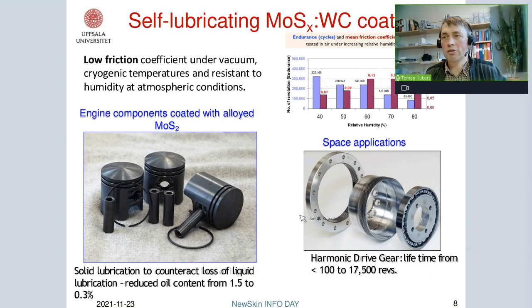Anyway, I start from an example of a coating developed by Tecnalia, solid lubricants or self-lubricating coatings that can provide surfaces with very low friction. And here are just some examples of the components. I will not go much into detail, but the advantage of solid lubricants is, as you may know, that these surfaces satisfy low friction even in the absence of lubricants. So they can increase the lifetime, reduce friction, and also prevent damage in case there is loss of oil or lubrication.